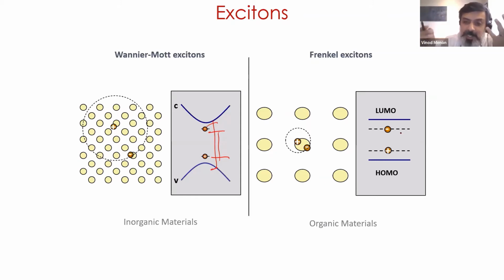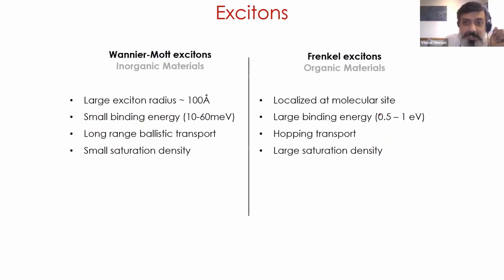But in the case of organic materials, you don't talk about a band gap, you talk about molecular orbitals. So this is the highest occupied molecular orbital, and this is the lowest unoccupied molecular orbital. And the exciton that gets produced in these systems sits again at an energy that is lower than the energy difference between the HOMO-LUMO levels. So these are the two broad classifications of excitons.